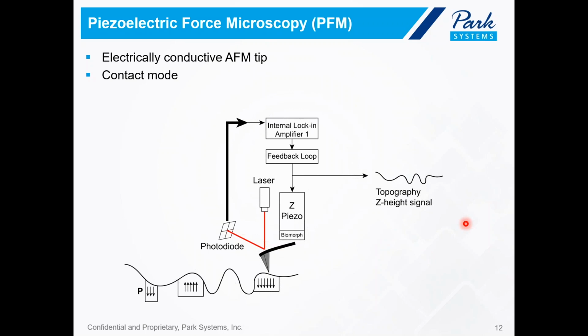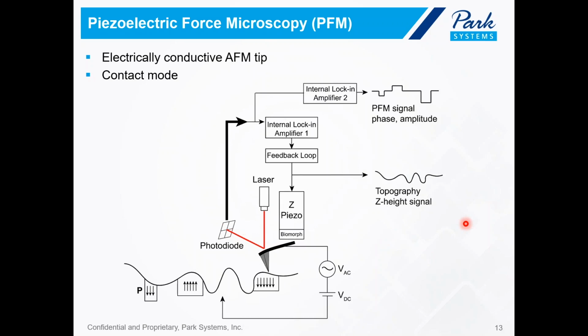As you can see here, topography or the Z height information. But if we want to get the piezoelectric response, we need to have a second lock-in amplifier, which will allow us to read out the PFM signal, including the phase and also the amplitude. So in a PFM experiment, an AC bias is applied to the tip, as you can see here.